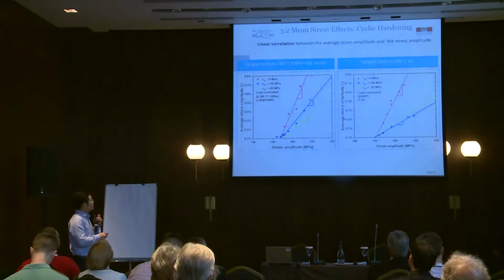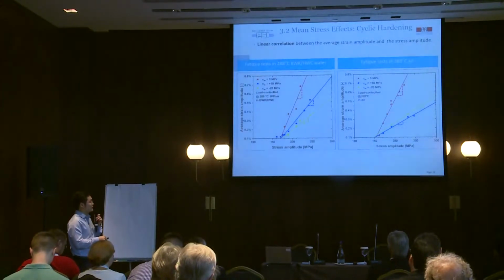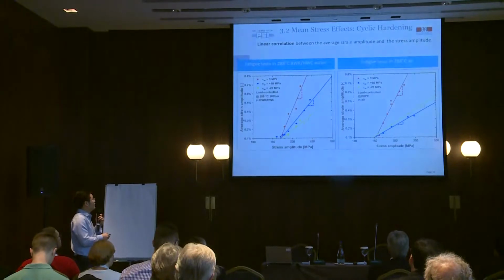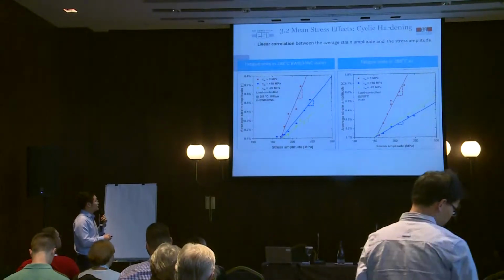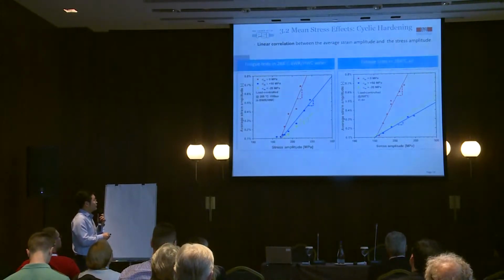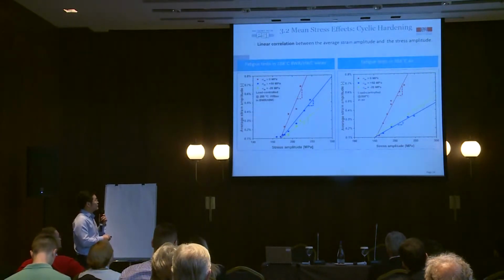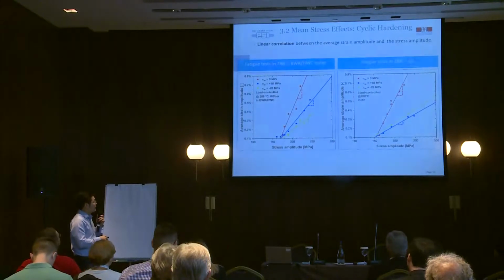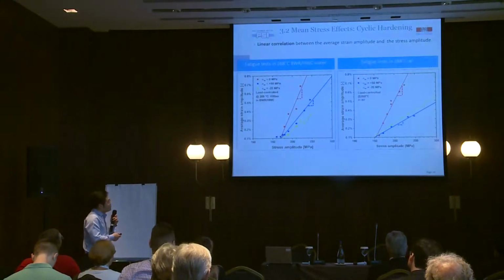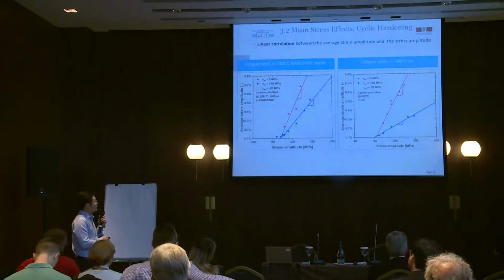we found that the slope with 0 mean stress and the slope with minus 20 mean stress are almost similar in the two different environments, but the slope of 50 MPa mean stress in high temperature water is bigger than the one in the air condition, which contradicts the hardening and the fatigue life increase effect of cyclic hardening.